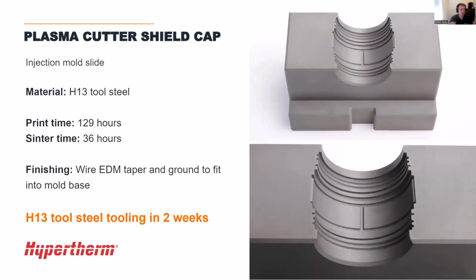What happened? They worked with Mantle here. This is actually a slide component that we can print. This is a relatively big part, I would say, for us, but you can see this is a slide that was used to, you can see here, obviously it doesn't fit perfectly because the part shrinks after it comes out, but the slide for making the outside of this component, this was printed in our H13 tool steel, which gave it that hardness needed for the glass-filled material, as well as that high temperature cycling that you were going to see during this molding process.